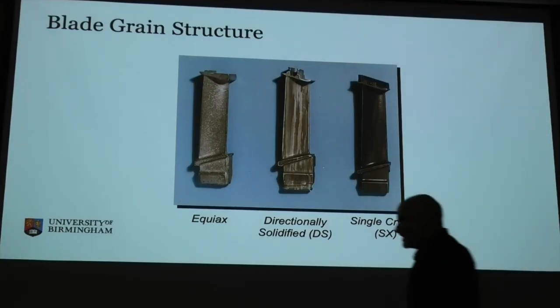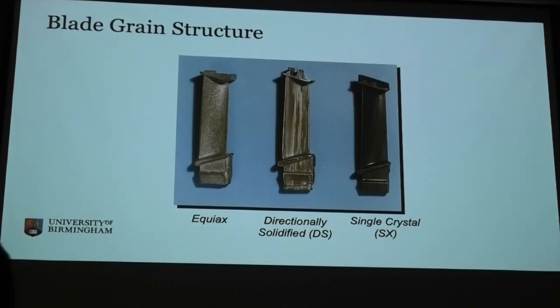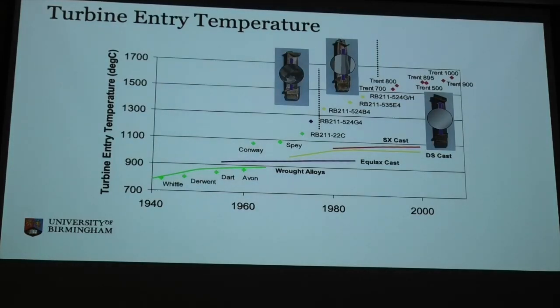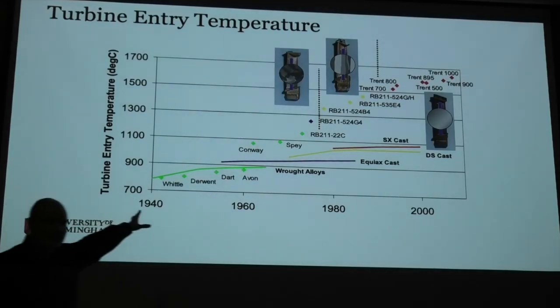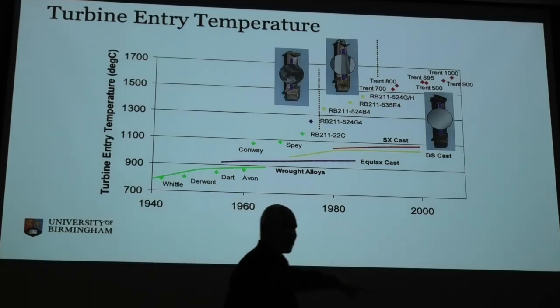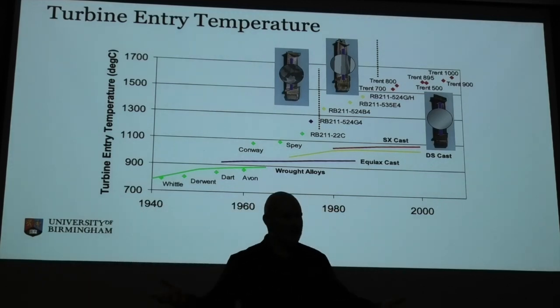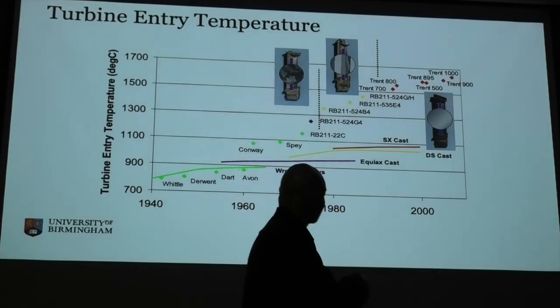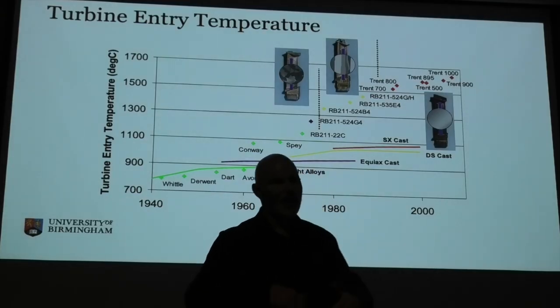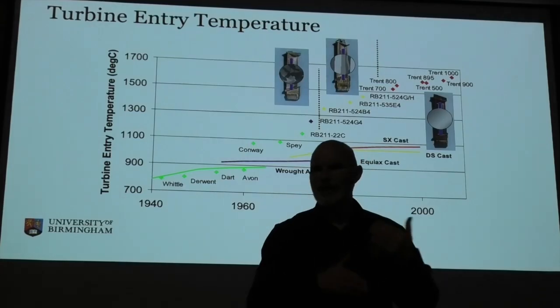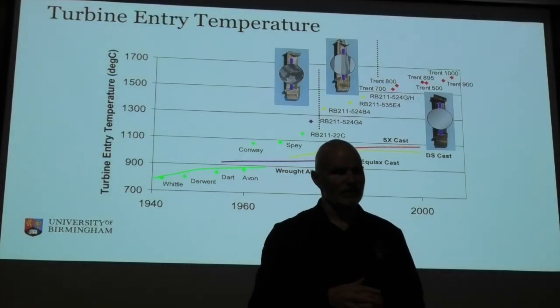So we went for single crystal. We have really taken every kind of opportunity. We had the metallurgist's guidebook to make strong alloys, and we've done the extreme. We've thrown the kitchen sink at them and made it ridiculously hard for ourselves, but we've done it. What that means is we've gone from wrought alloys, standard forgings, equiax cast - just pouring it in a mould, letting it solidify - to directional solidification, and then single crystal casting. Each time giving us a few degrees more of temperature capability that we've squeezed into the engine.